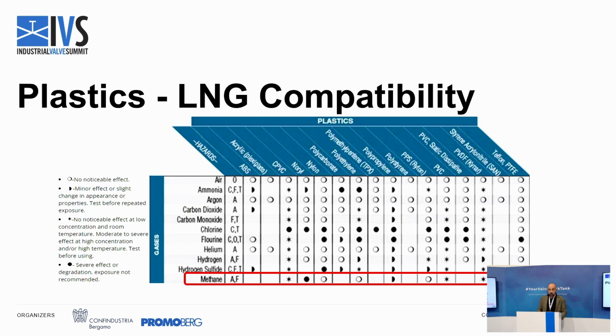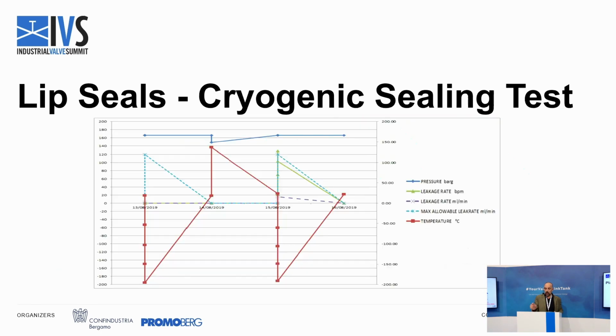with methane. And the point is, again, that there is no certification whatsoever for the lip seals or the plastic sealing in a valve. It does exist the BS 6364, which is a specification for the valve in the cryogenic sector, for the cryogenic service. But it's not a test that requires some performance from the seal. It doesn't require anything from the seal. It requires, of course, that the valve should not leak, so the seal should work. But there's no test on the seal itself.